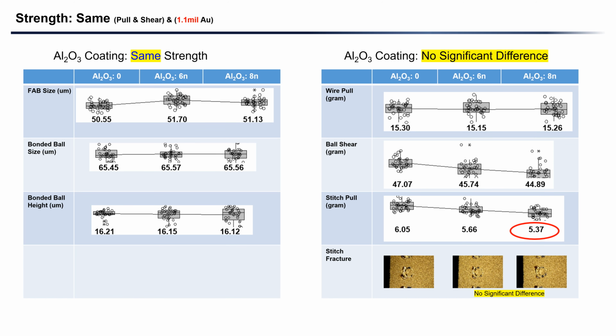Here I'm showing you bondability data for the 1.1 mil gold wire having an aluminum oxide thickness of 0, 6 nanometer, and 8 nanometer. Fab size is the same. Bonded ball size is the same. Bonded ball height is the same. And we found the strength is the same as well: wire pull strength, ball shear strength, stitch pull strength. There's a little bit of a drop, but looking at the stitch fracture mode, they are all the same.